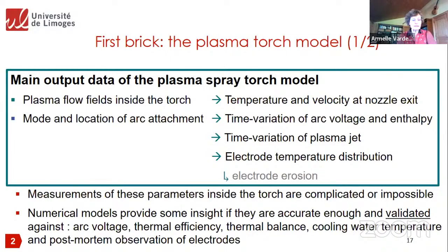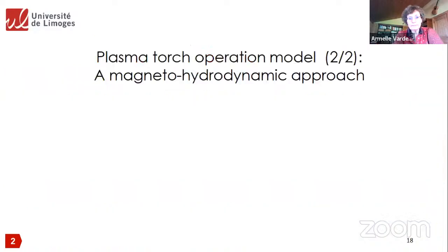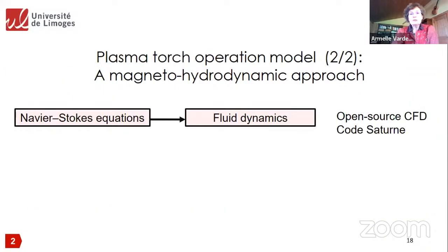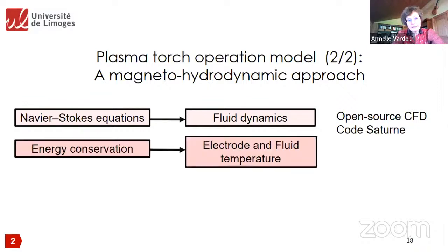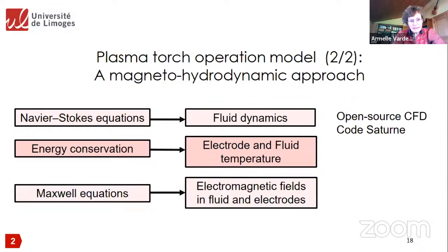And for that, what can we use? We have the arc voltage, the thermal efficiency of the torch, the thermal balance, but also the cooling water temperature and the post-mortem observation of the electrodes. All the models dealing with plasma torches for spraying, cutting, welding use the same approach, that is a magneto-hydrodynamic approach. So we solve at the same time the Navier-Stokes equation, the heat equation, and the Maxwell equation. And these equations have to be solved simultaneously.